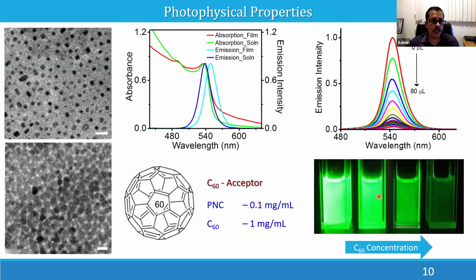Here in the first TEM image, you can see the nanocrystals. They are isolated nanocrystals. So in a solution, it is like an isolated nanocrystal. And into this isolated nanocrystal, we added C60, that is fullerene. And we were able to see significant quenching of the emission that you can see here. This is the initial emission, and after adding something, the emission quenched, and with further addition, the emission is further quenched, and then it is a significant quenching by adding almost 1 milligram per ml of C60.